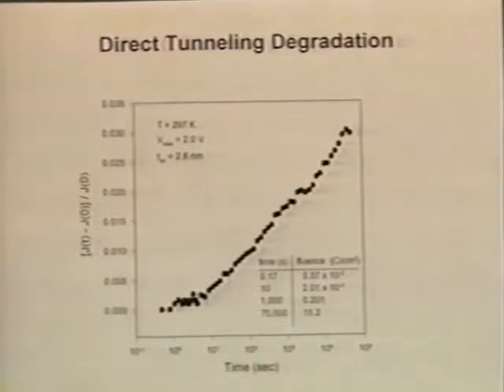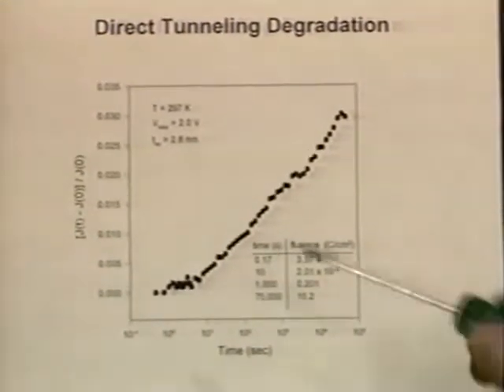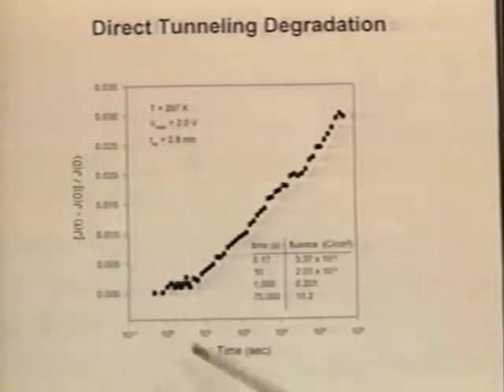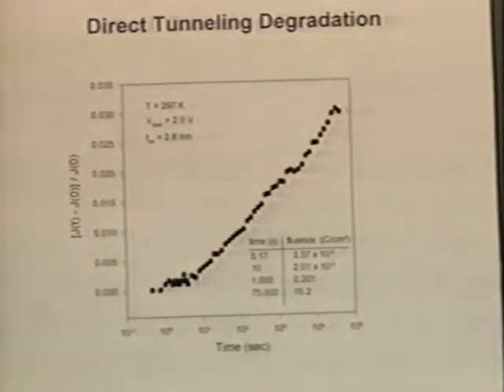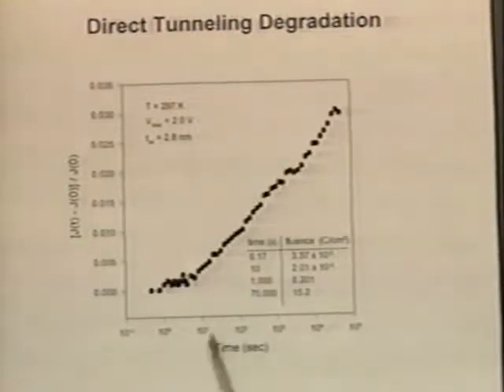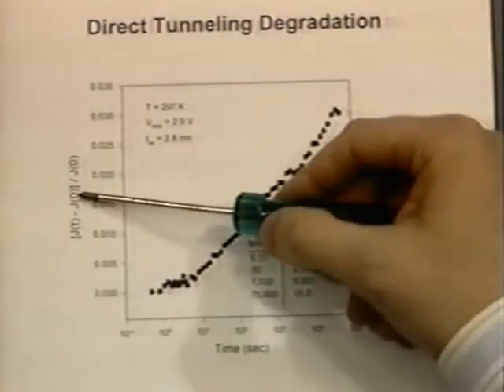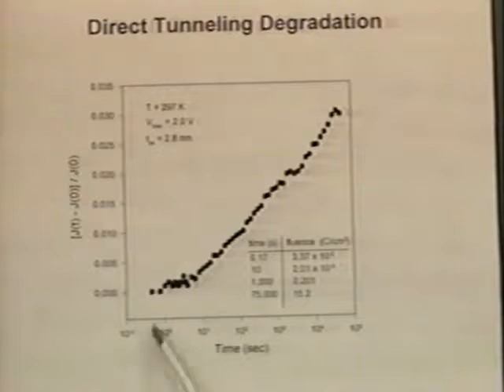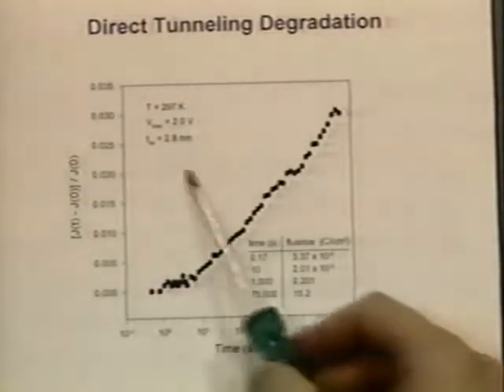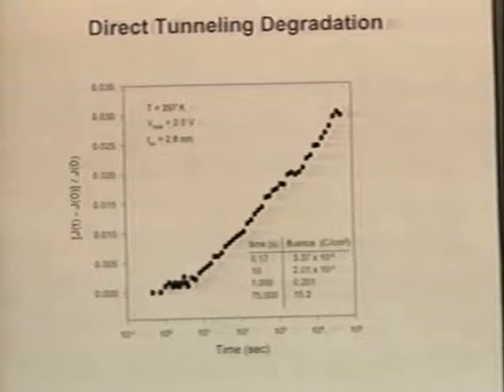Okay, so I want to start right out with an instability. Call it direct tunneling degradation. What I'm plotting here is the fractional change in the current versus time. Now, if there's nothing happening in these oxides, you sit at a constant voltage, and what happens to the current? Nothing. Nothing should happen to the current. But instead, what we see is that the current is gradually increasing over time. You take the current as a function of time, subtract the initial current, and normalize by the initial current, and you see that after about 10 to the 4th seconds, there's a 2 or 2.5% change in the current. It's a subtle effect, but the current is gradually increasing.